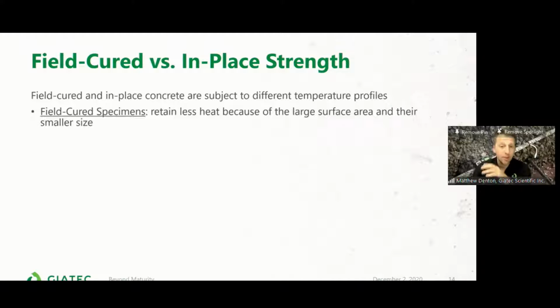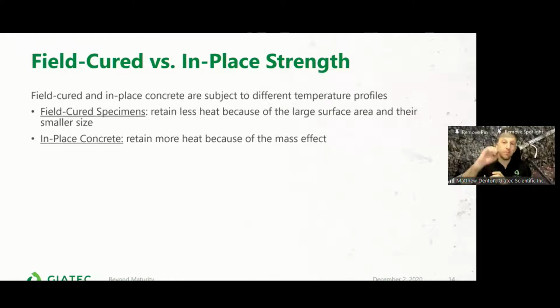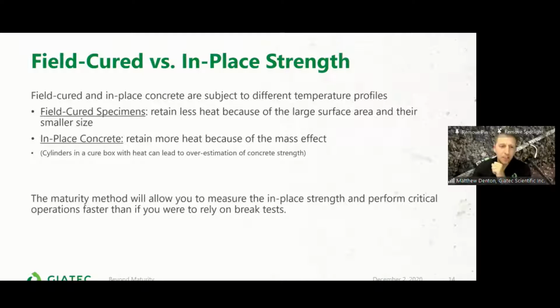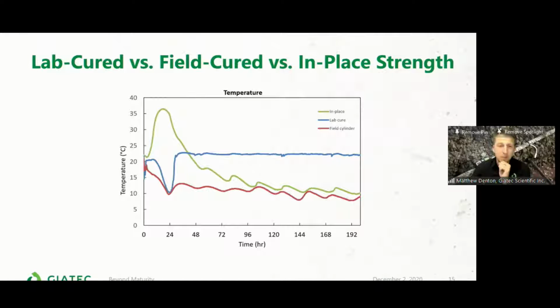I don't want to spend too much time on this slide, but essentially what we're saying is that because of the field cured samples that we're taking, they're much smaller, they retain much less heat, and therefore the difference between the field cured and the in-place is that massive spike in the temperature that we often see in the first 12 to 24 to even 48 hours in many cases. All right, I'm going to jump forward a little bit here. I don't want to spend too much time here.